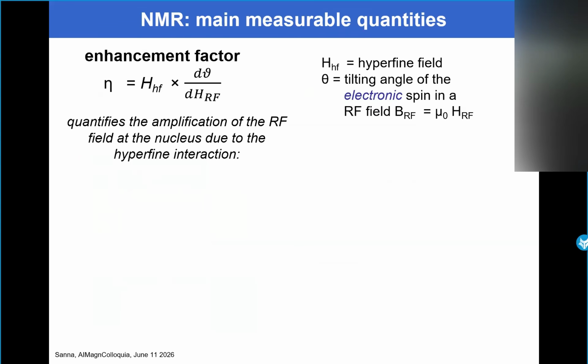But another important parameter that we can measure by using NMR in ferromagnets is a less known parameter, which is the enhancement factor. The enhancement factor is a parameter which is defined this way, where here we have the hyperfine field, the tilting angle of the electronic magnetization, and the radio frequency field from the coil that we have already mentioned. Actually, this parameter quantifies the amplification of the radio frequency field at the nucleus due to the hyperfine interaction.